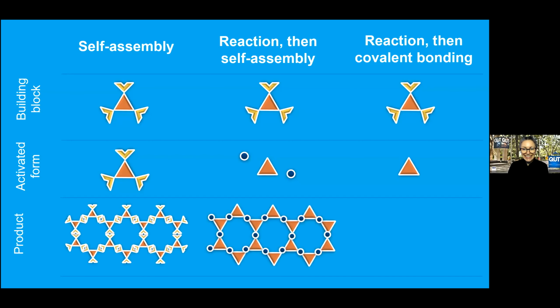And here you see a self-assembled structure where instead of the original building block, we're now using a modified one, but non-covalent interactions to assemble it. And typically, this would be metal organic or organometallic interactions on the surface. So these blue dots would be representative of atoms. I'm just looking at my self-assembly, it's not very good. It's a little bit of a defect in there.